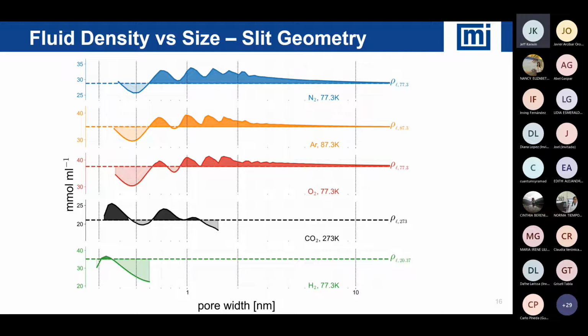But once we get up above 1.1 or 1.2 nanometers, the density drops off quite quickly. And this is at ice temperature. So CO2 is going to be very effective below 1.1 nanometers for adsorption. And then finally, at the very bottom, you see how effective hydrogen can be in some of the very small pores. So as we approach 0.3 nanometers, we can get quite significant densities of hydrogen in a 0.3 nanometer pore. But as soon as you start approaching 0.5 or 0.6 nanometers, the hydrogen density is quite low.